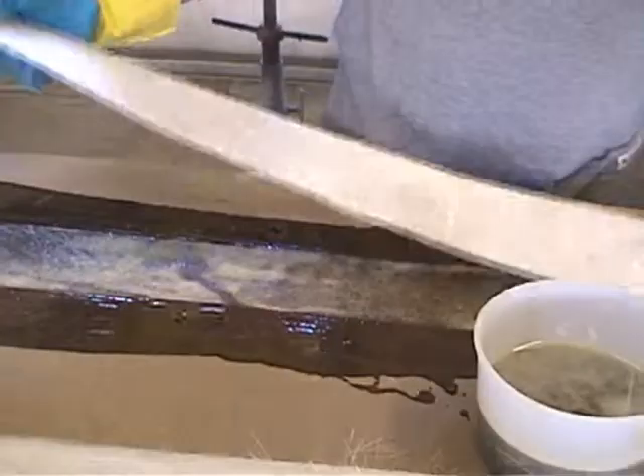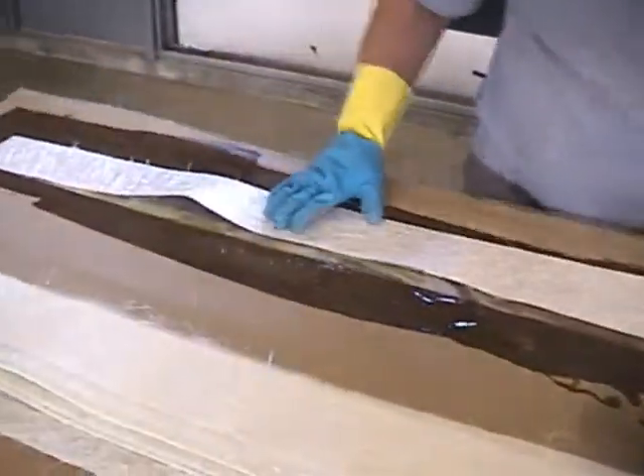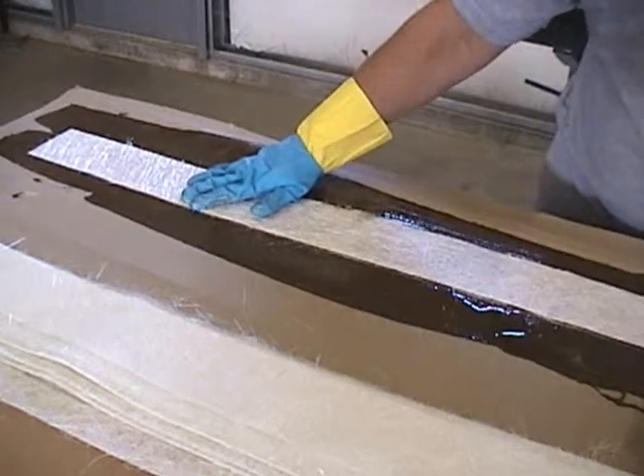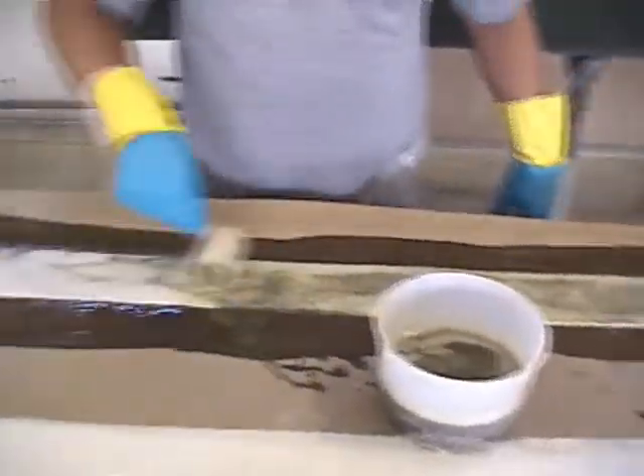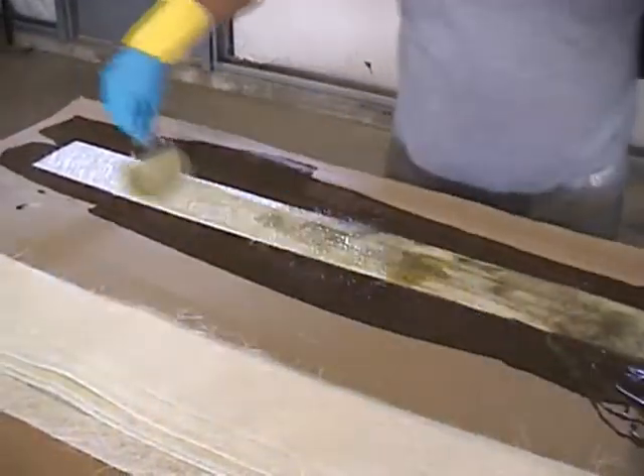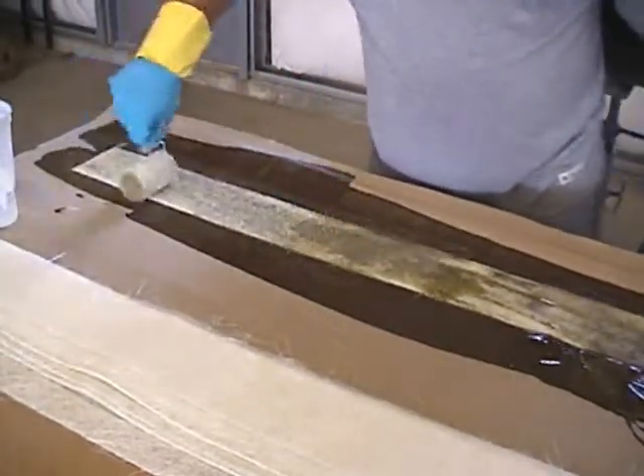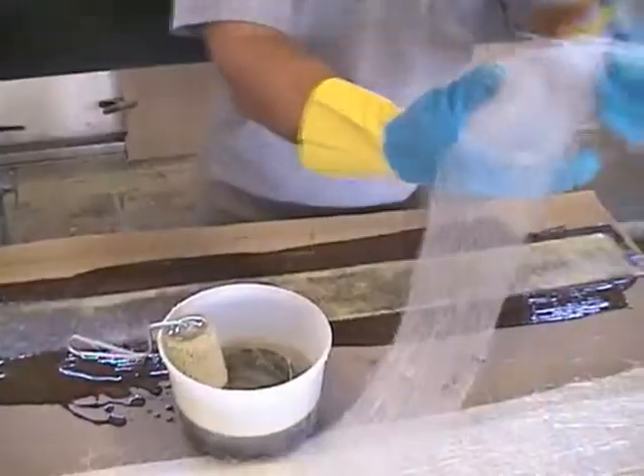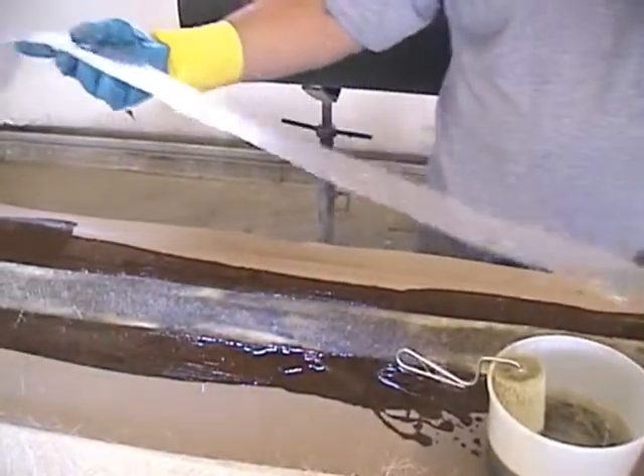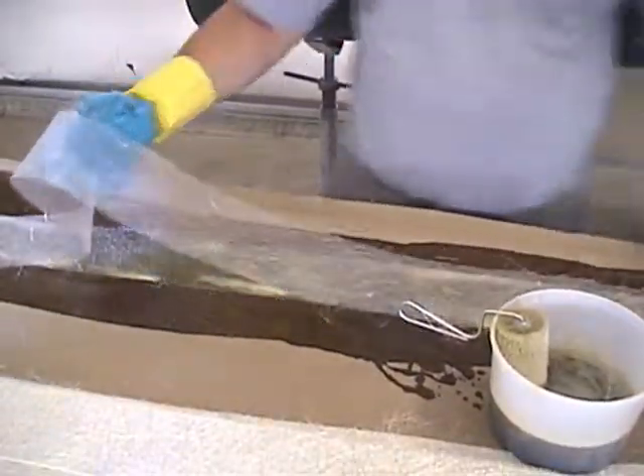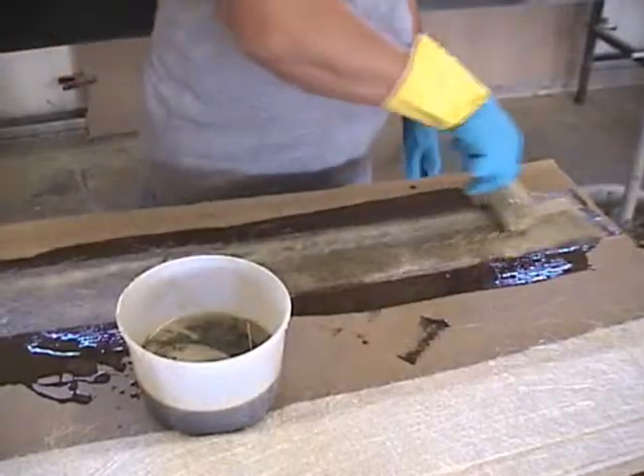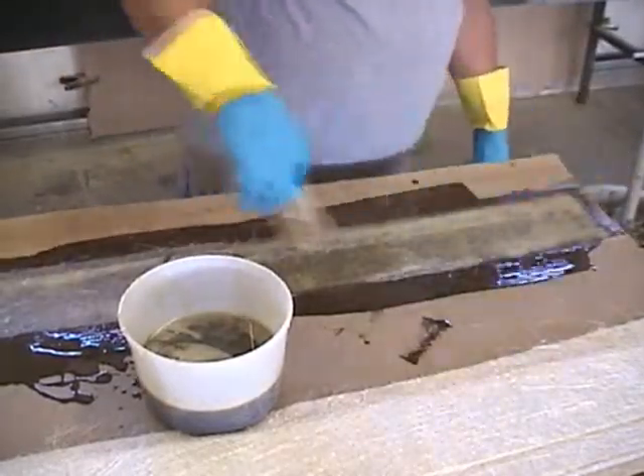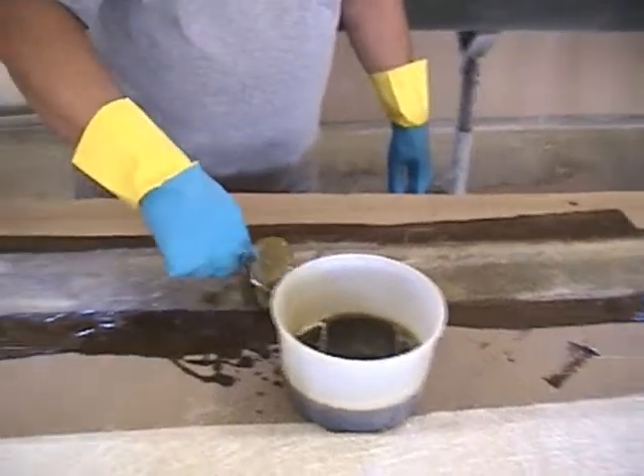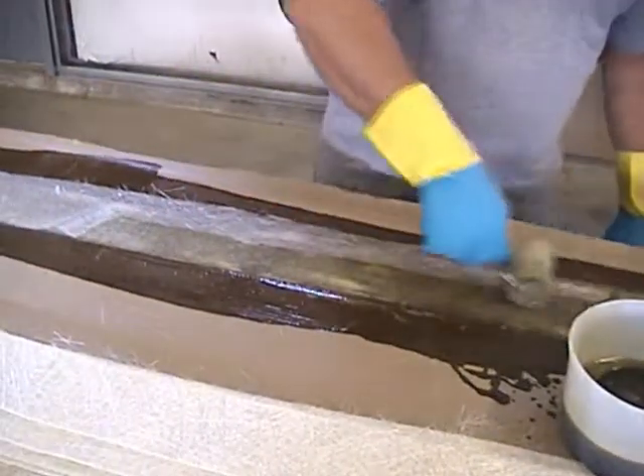Lay down your first chopped strand. This is your liner. We're going to do what we call an outside tie-in. Put the chopped strand down and the veil up. The last piece of your liner is the veil material. Put it on top. When you wet this material with the veil out, roll in one direction, not back and forth. Be careful not to add too much resin to your glass.